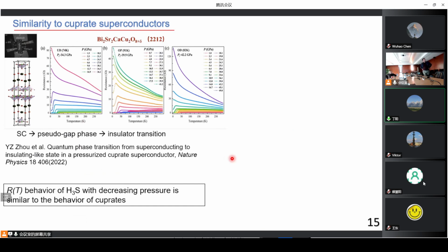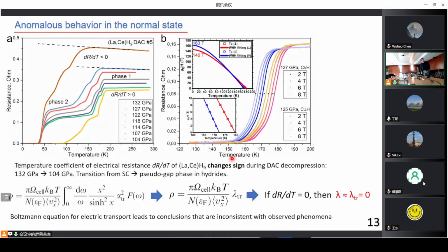Is this BCS type or non-BCS type, according to your experience? According to my experience, it's 90-95% that this is BCS-like theory, Migdal-Eliashberg theory, and the main mechanism is of course electron-phonon coupling in hydrides. But the behavior in the normal state is not metal-like and cannot be described within Fermi liquid theory. That's a big difference. So in this case we should apply a different theory, and Fermi liquid cannot be applied.